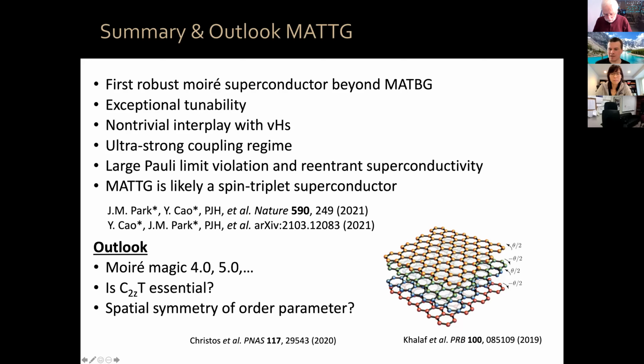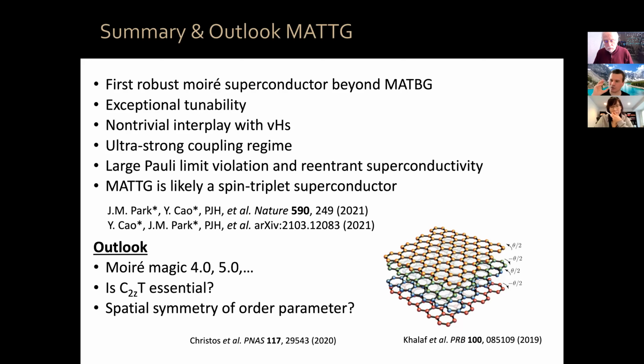Now, in this work, actually not in this paper, in a subsequent paper that I haven't listed here, the group of Ashvin Vishwanath proposed a new mechanism for superconductivity. It's entirely due to Coulomb interactions, and they call it skyrmionic superconductivity, where the Cooper pairs are actually pairs of skyrmions. They form a BEC of skyrmions, and they claim that for that mechanism to work, they need to have exact degeneracy between two sets of Chern bands. In order to have that degeneracy in that Chern sector, they need to have that C2Z symmetry and also T. So they need to have C2Z T symmetry. Otherwise, those Chern bands are not degenerate.